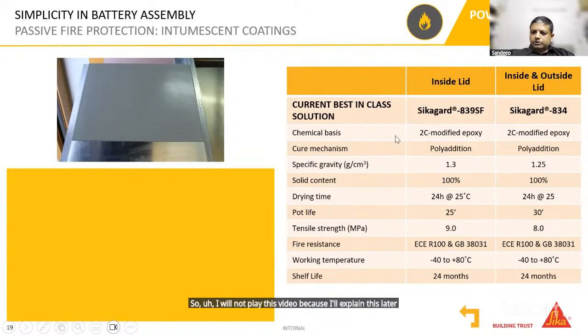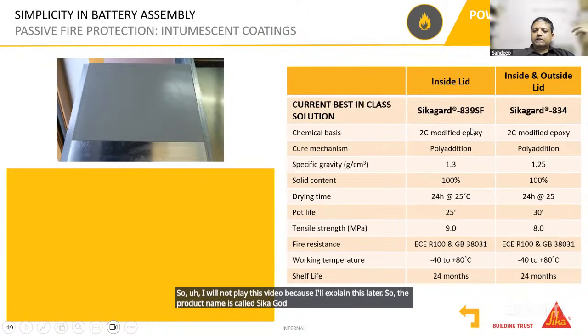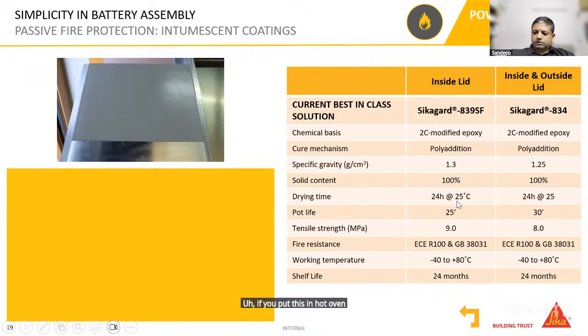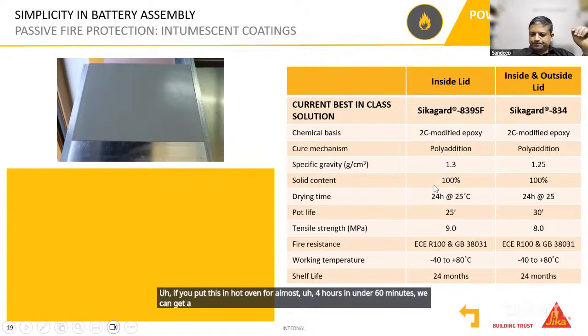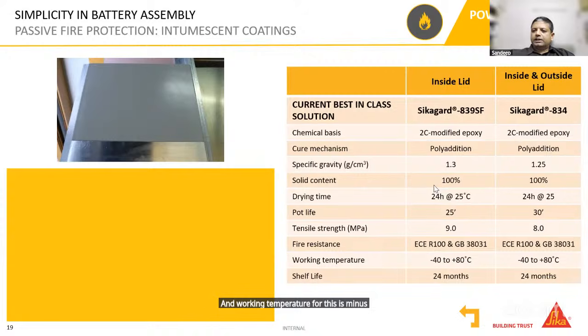So the product name is called SikaGuard 839, which is basically an epoxy-based solution. And like I said, this has got a curing time of almost 24 hours, but this can be accelerated. If we put this in a hot oven for almost 4 hours, in under 60 minutes we can get a completely cured material. And the working temperature for this is minus 40 to plus 80 degrees Celsius.